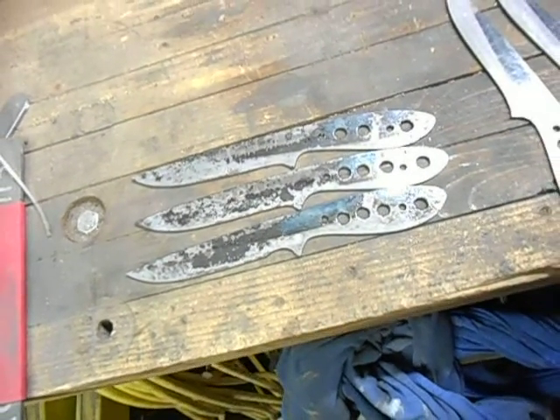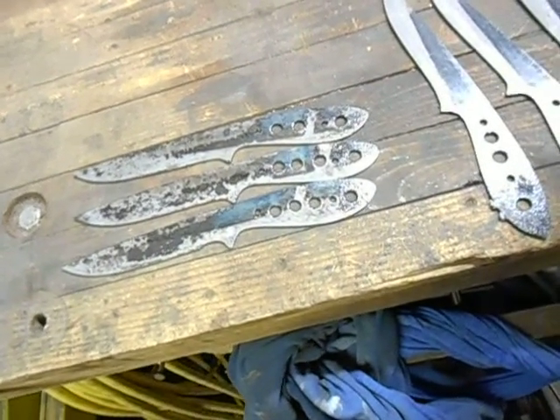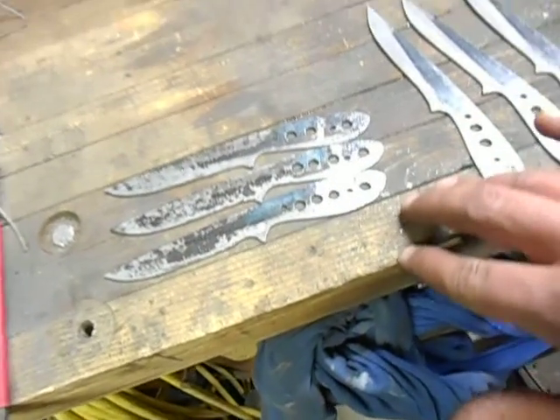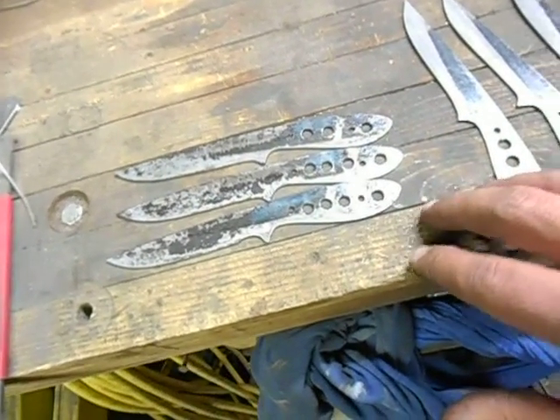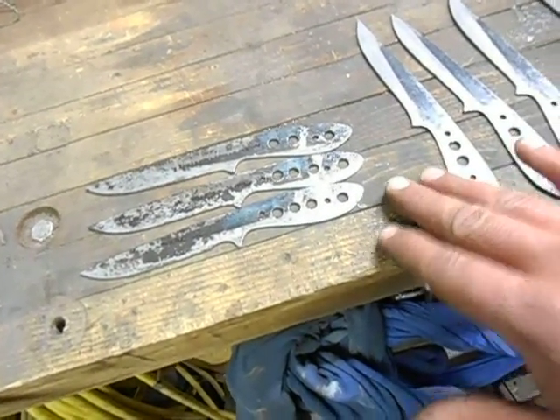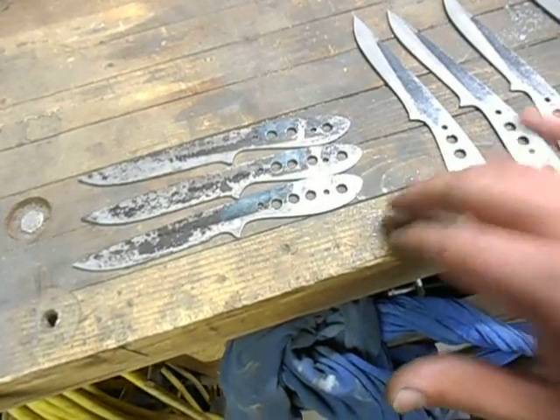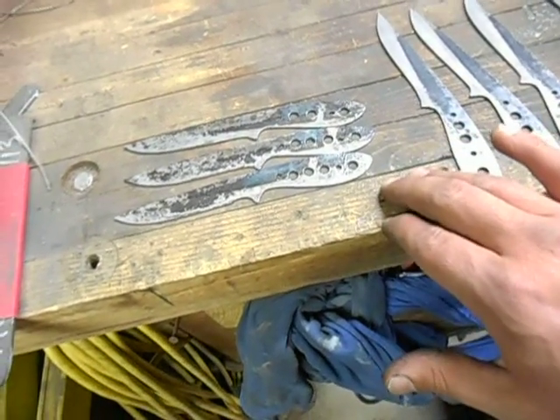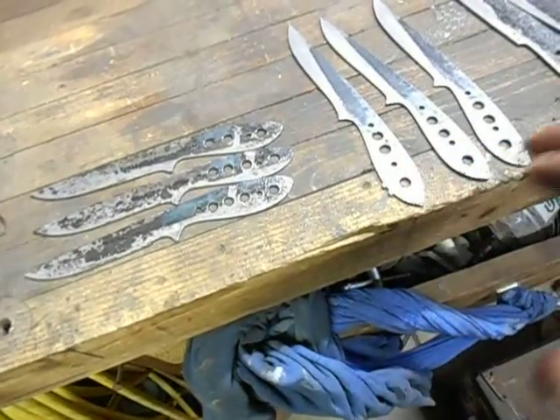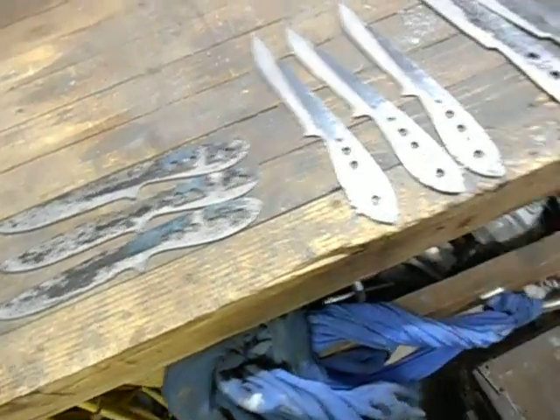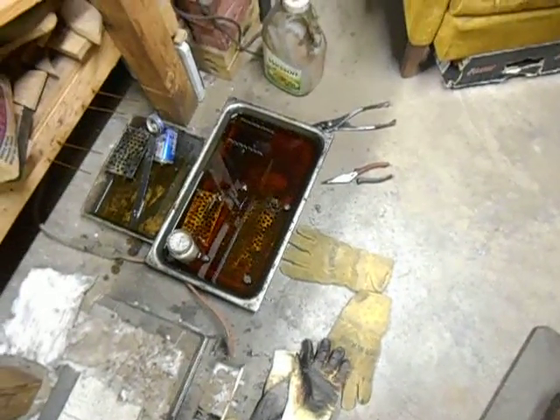Now the kiln is heated up to 1500 degrees Fahrenheit. The 1/16th inch thick blades are placed in the hot kiln. The timer's set for 7 minutes, and at the end of the 7 minutes they're pulled out of the kiln and they're edge quenched into 130 to 140 degree canola oil.